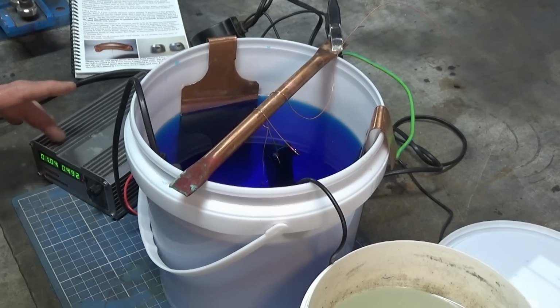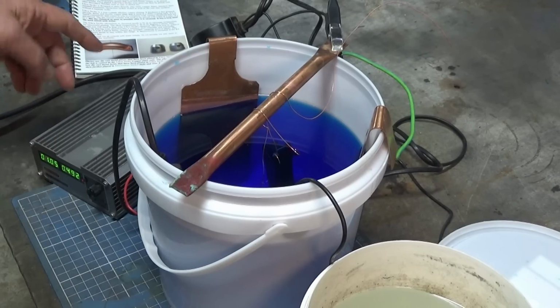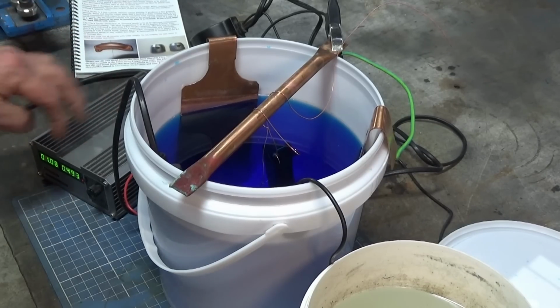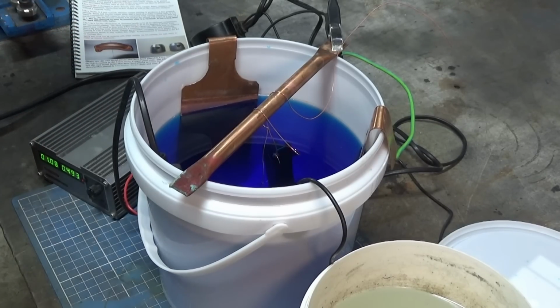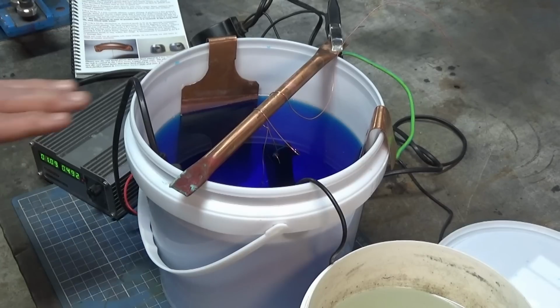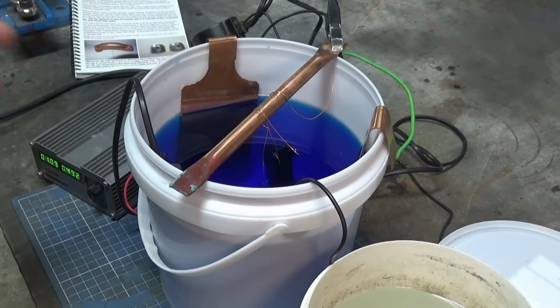And the power supply is showing 1 volt, even though I've got it set to 2, but it's drawing the full half amp now. I may just run the amperage up a little bit. I'm going to leave them in for probably 10 or 15 minutes. If you leave it in longer than that, you get a thicker coating of copper, but it also starts to form a sort of sludge on the surface. So we're just getting a very, very thin coating of copper so that the nickel cobalt will actually work.